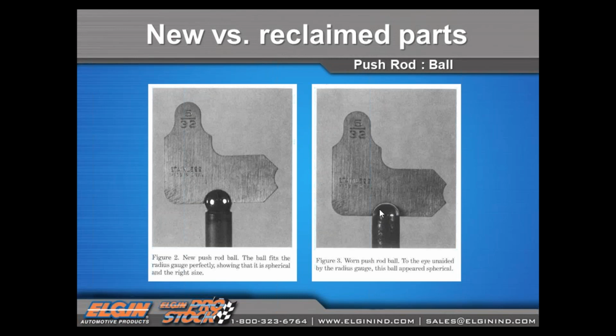So even though you might have heat treated material left that would survive, you're going to concentrate all your wear on these outside edges. And what happens when you do that in a rocker seat? You burn through the rocker and it punches the seat out, like we saw in that first picture.